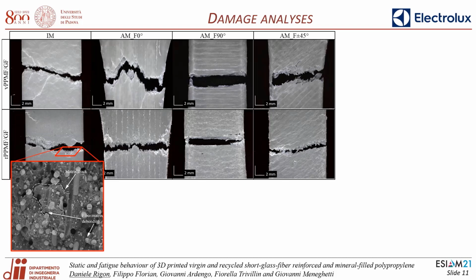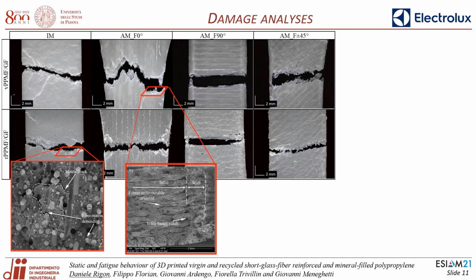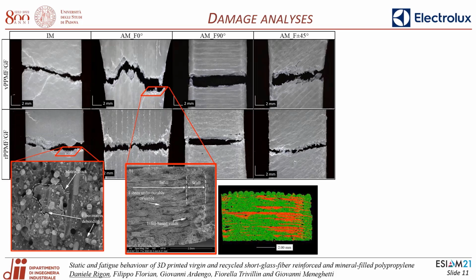In the case of virgin F0 and recycled F0 specimens, the failures initiated at the start point of the fillet, due to the presence of voids at the interface between the wall and the infill, and by the presence of the defects generated by the peculiar infill strategies already presented, which cause a weak point in the material. The fracture then propagates in a zigzag appearance, more pronounced for virgin than for recycled specimens, due to the interlayer delamination and the bonding of adjacent filaments.